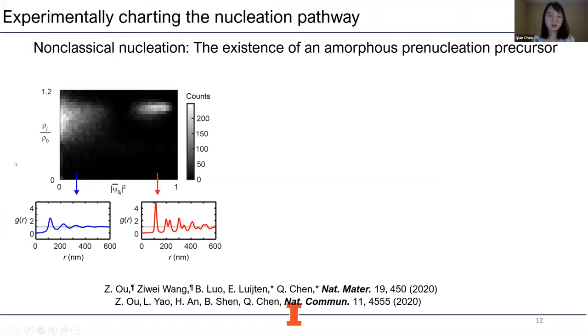Because we have a lot of columns and a long movie, we can plot out a probability map in this order parameter space. So if you look at this 2D map here, your eyes can see two populated states. And interestingly, beyond this one state with a high structure order and high local density, which is our final crystal, we also have another state with no structure order and high local density. And that's our amorphous pre-nucleation precursor.